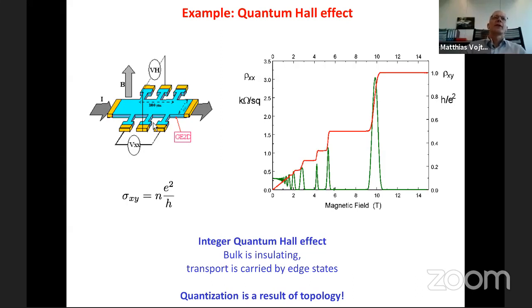You put a two-dimensional electron gas in a perpendicular magnetic field as shown here, and you measure the Hall voltage if you drive a current through the sample in a perpendicular direction. And if you plot the resistivity or the conductivity, you see that the Hall conductivity has precisely quantized plateaus, which follow this quantization rule down here. And this number n is an integer, and it's an integer because of topology.